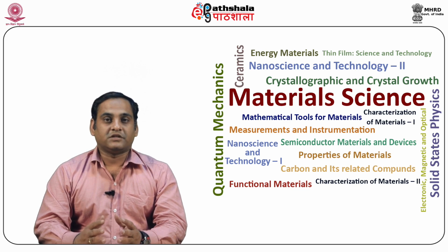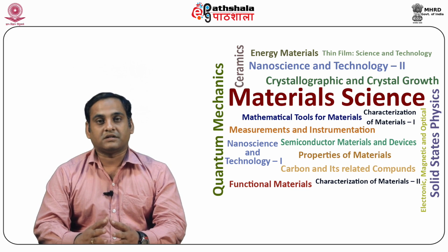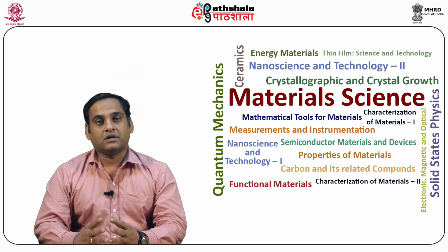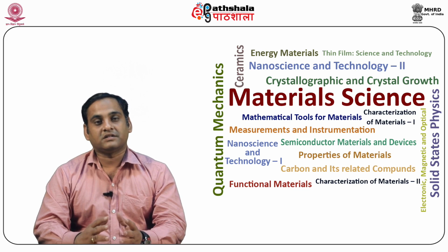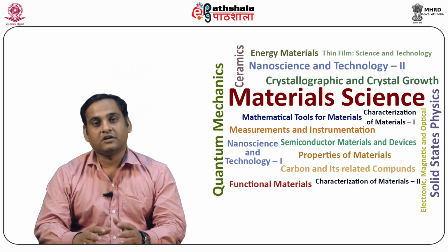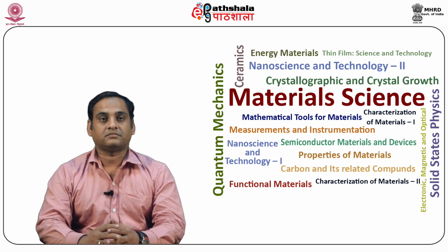Alternatively, in the absence of an external electric field, it is reasonable to expect that the excited electrons can return to their ground states by the emission of a photon of light. Luminescence is actually observed in additively colored alkali halides. However, it is necessary to maintain the crystals at low temperatures so that the electrons are not thermally excited to quantum states in the conduction band.